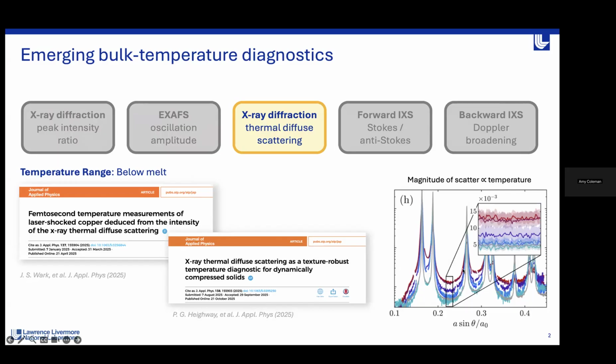Temperature increases inelastic phonon scattering between these Bragg peaks, and the intensity of this diffuse scattering scales with the phonon population. By fitting it, and again by using a Debye-Waller framework, we can infer a temperature.